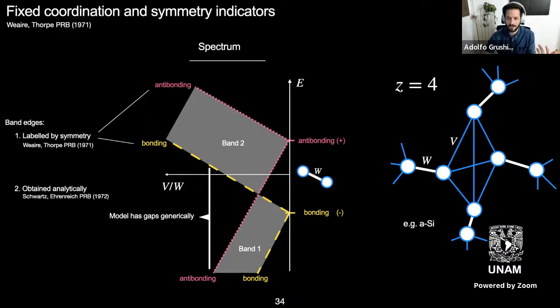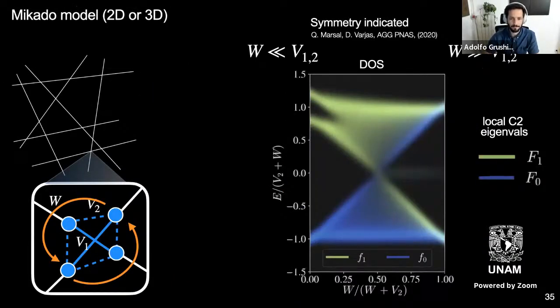And in fact, these models are sufficiently simple that you can kind of analytically solve for the gaps. And that's how Weaire-Thorpe showed that basically windows were transparent in this specific model. And now we're going to do the same thing, because this is kind of like a planar version of the Weaire-Thorpe model that I just showed. And there's a symmetry that is inversion with respect to C2, with respect to this molecule. And you can plot the density of states projected with a color that tells you how well the eigenstates match this C2 eigenvalue. So this is the plot I'm showing here.